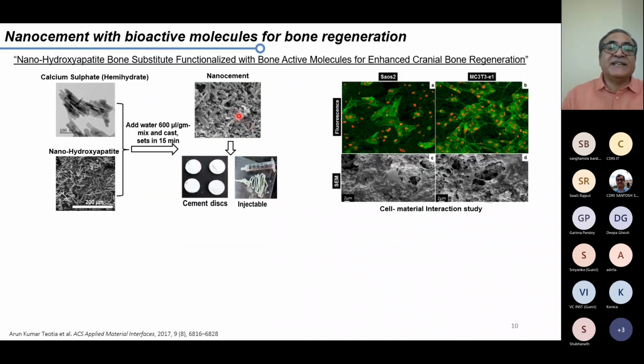So let me start with the first example, which we started some time back. As I said, we developed in-house calcium sulfate hemihydrate and nanohydroxyapatite. These are the two materials. If you mix them in a 60 to 40 ratio, 60 calcium sulfate hemihydrate and 40 nanohydroxyapatite, with 600 microliter of water per gram of the mixture, you develop a paste. This paste is exactly like a toothpaste, and it can be filled into the voids, and it sets in 15 minutes like a cement.